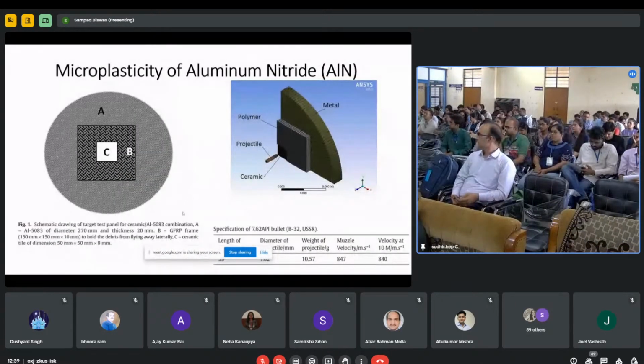So our projectile was about 10.57 gram weight, and it hit with a muzzle velocity. Muzzle velocity means, when you take a gun shot, you can change the muzzle velocity by changing the composition of the explosives. By changing it, the maximum muzzle velocity can go up to 847, and we did the experiment with the highest muzzle velocity of the projectile. It is about 847 velocity, and it happens with any AK-47 bullet. So that was our technical interest.